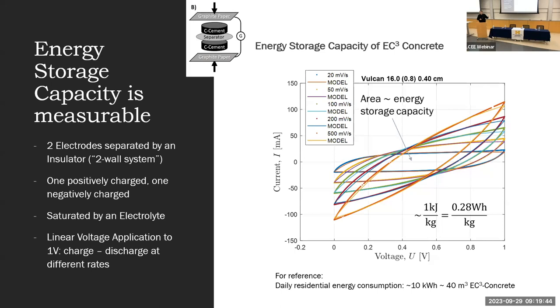Now, these are typical results from electrochemical testing. Here, a test in which we impose the voltage up to 1 volt. Never use more than 1 volt because of the electrolyte, the salt solution, which is water-based. You don't want the water to split into hydrogen and oxygen in your material, so you never go above 1 volt. And the area here, in this plot where you charge and discharge, is a measurement of the storage capacity of the system.